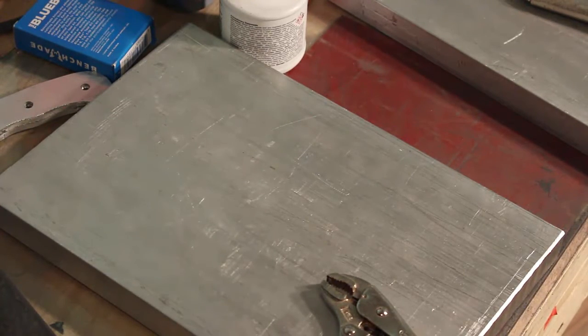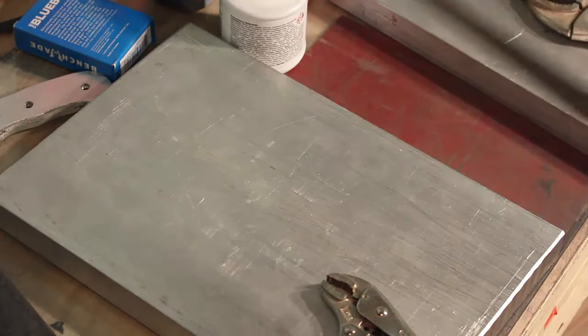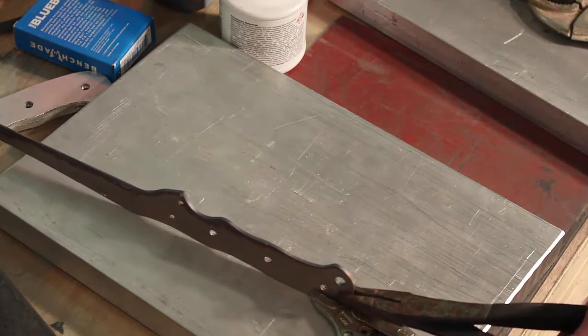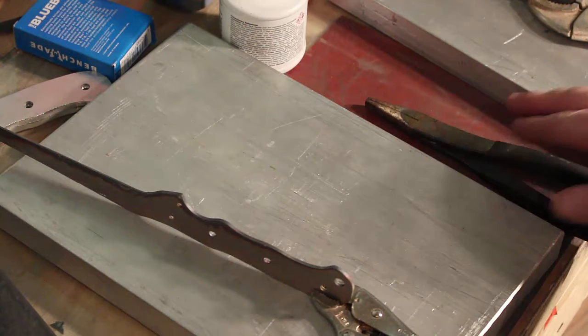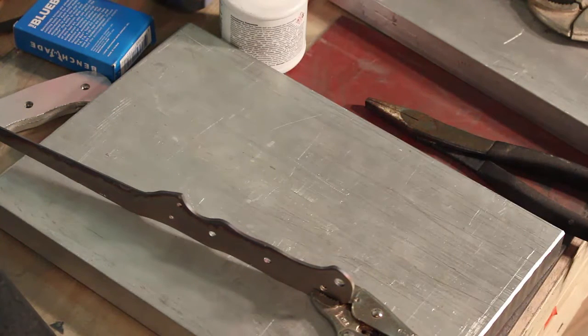First temper is just about done. 1 minute to go. I have the vice grips on the plate because that's where I usually set it up to let it cool. I probably could set it flat on the aluminum, but I'm not sure. I just do it this way. Then let them cool to room temperature, and do it all over again for another 2 hours. This time I ended up doing the temper at 450 degrees for 2 hours to see if maybe I get down to about a 60 or 61 Rockwell. We'll see in another few hours. Alright, let them cool and back at it again.